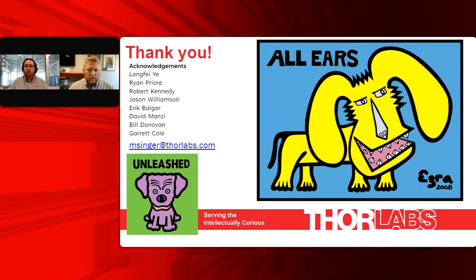Matt, can we reuse these, or can you clean these once you've deposited your sample on them? Yeah, great question. So unfortunately, we cannot clean these. If a customer buys them and wants to attempt a cleaning process, you are more than welcome to. We would love to hear the feedback for how these can efficiently be cleaned. The reason is that certain molecules will bind very strongly to the gold surface where others won't. Depending on those molecules and the cleaning method that you use, it may strip away the gold, it may strip away the molecules, it may functionalize the surface in some other way. So we cannot guarantee that the performance would be maintained if you attempt to clean them.